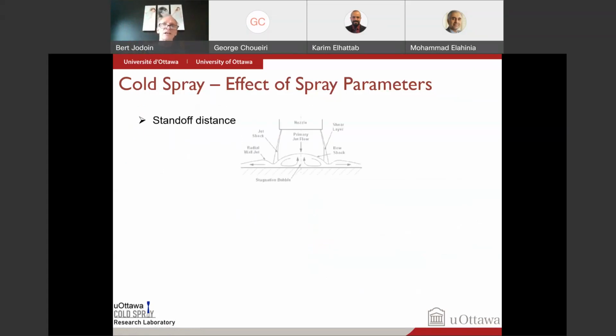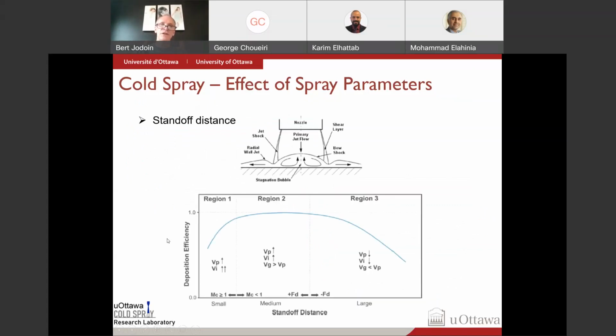Another parameter is the standoff distance. So the standoff distance is the distance between the nozzle and the part that you want to coat. Because the flow is supersonic, you're going to get a shock wave here, which will be detrimental. So if we look at the deposition efficiency, if you're very close to the nozzle exit, the particle velocity is not very high, the deposition efficiency is not very high.